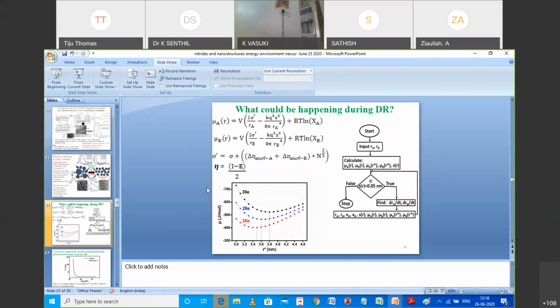As engineers, we also like to model this. So we wrote out equations and did self-consistent field calculations. Believe it or not, this was done by using a free software, and I used what's called an agent-based software. It's a very easy to learn language. And once you learn it, you can actually play with these equations. Now, these equations are colloidal chemical equations. The first part, if you have taken a course on colloidal chemistry, you might recall is called the Gibbs-Thomson part. The second one is to do with mixing entropy. This part was added in by hand because these particles have electrostatic interactions.